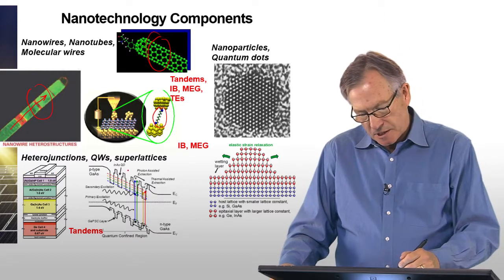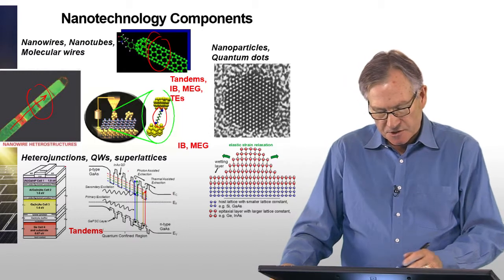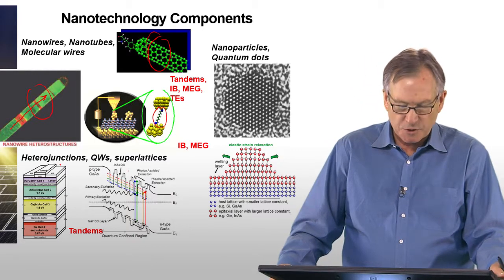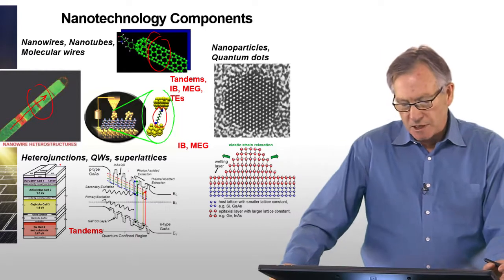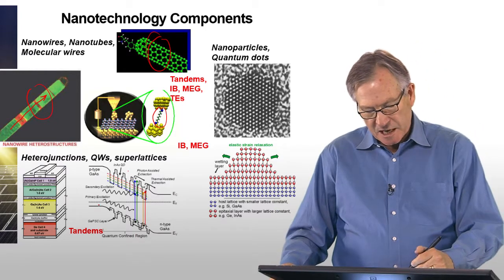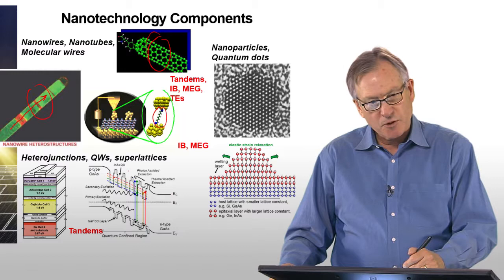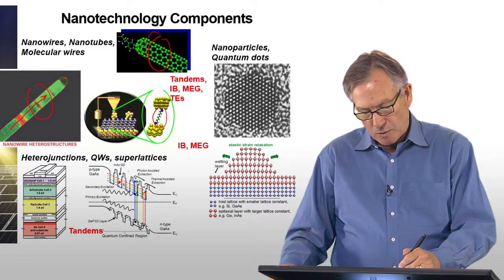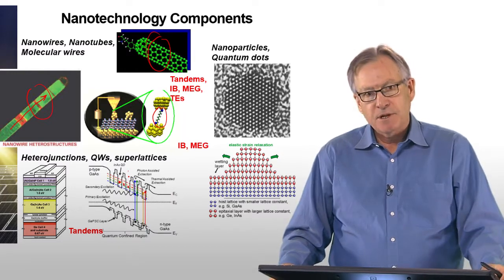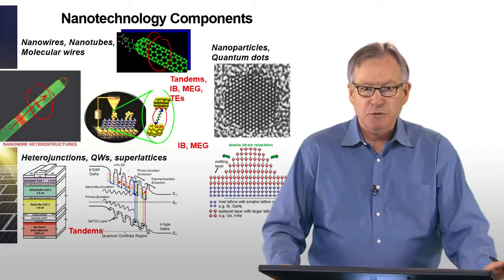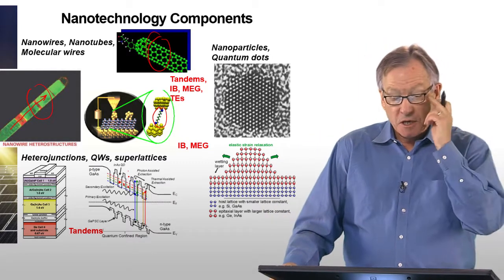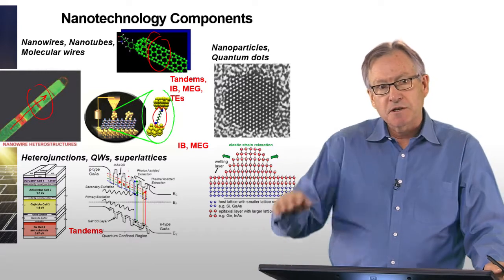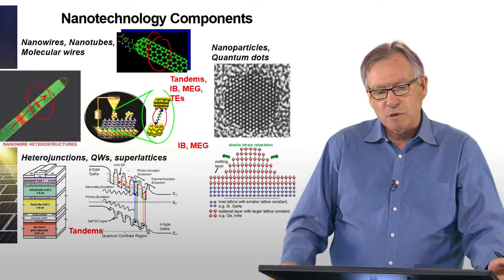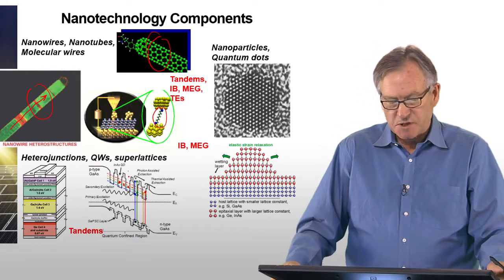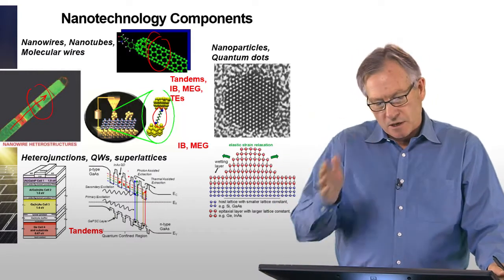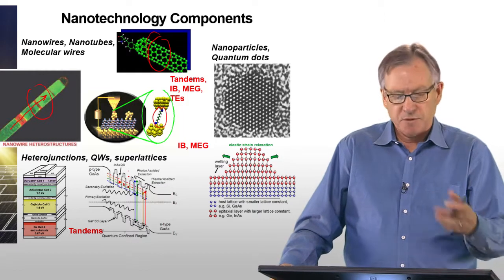And it's basically realized, so what's shown here is a schematic of what's called a superlattice or a multi-quantum well system. And this is realized by taking a material with a wide band gap and sandwiching it with a narrow gap material, and then growing another wide band gap material, narrow gap, wide band gap, narrow, et cetera, et cetera. You can do this with a process called molecular beam epitaxy, which essentially is a layer by layer growth technique in which you grow atoms one by one. You grow layers one by one on the surface of a semiconductor, and so you can control atomic layer by atomic layer the thickness of the material.